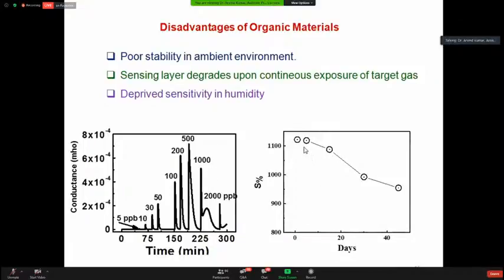Second, if we leave the sample in open condition or ambient environment and measure the sensitivity with time, the sensitivity is decreasing. So stability is a problem in the case of organic materials.